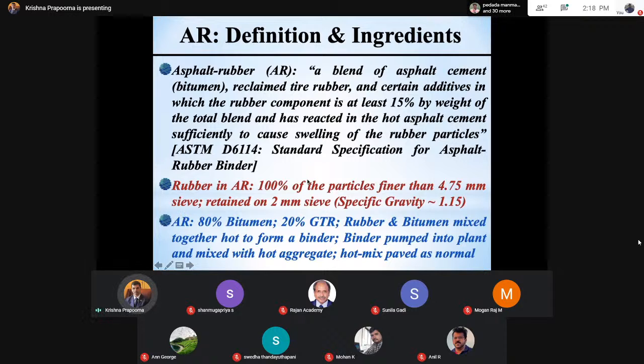Now, how much of rubber inclusions in the blend? You see, it has to be finer. You see, 100% of the particles finer than the demarcation line that distinguishes between coarse aggregate and fine aggregate, right? That's the 4.75 millimeter sieve. And it has to retain on the 2 millimeter sieve. This is what the rubber particle size is. Now, people have actually gone even lower than this.